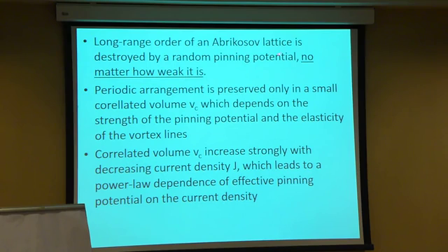They proved theoretically that long-range order of an Abrikosov vortex lattice is destroyed by random pinning, no matter how weak it is. So if we have random pinning in a material, no matter how weak, we will no longer have any long-range Abrikosov ordering. Now, this periodic arrangement is preserved only in a small correlated volume, which depends on the strength of the pinning potential and the elasticity of the vortex lines. The correlated volume increases strongly with decreasing current density, which leads to a power law dependence of the effective pinning potential on the current density.